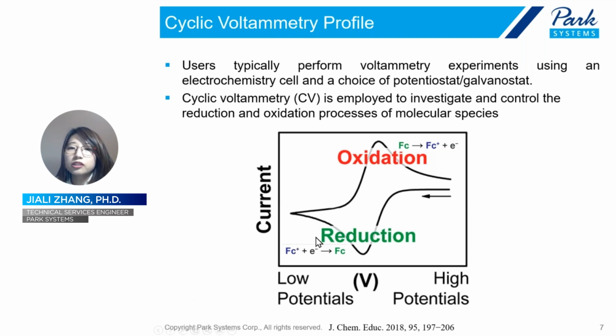For example, when a solution of Fc+ is scanned to lower potentials, it will reduce to Fc locally at the electrode. That results in the measurement of current and depletion of the Fc+ ions at the electrode surface. Then when the switch potential is reached, the scan direction will reverse and the potential is scanned to a higher potential, and the Fc on the electrode surface is then oxidized back to Fc+ as the applied potential becomes higher and more positive.